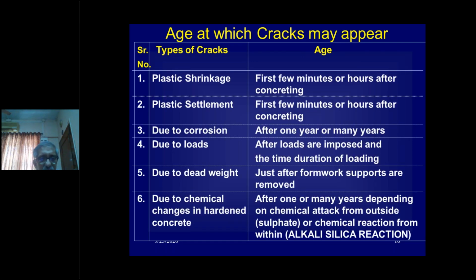The best way to judge a crack is the age at which it has appeared. So it is always very important that the consultant must visit the site of repairs. And if it's an occupied building, ask the occupants, when did you see this particular crack? And if the occupants say, oh, we have seen it right from the day we occupied, then it could be a plastic shrinkage crack or plastic settlement crack. Or if the occupant says, no, we saw it about 2 years back, it could be a corrosion crack, or it could be due to the load somebody has put extra in the building,